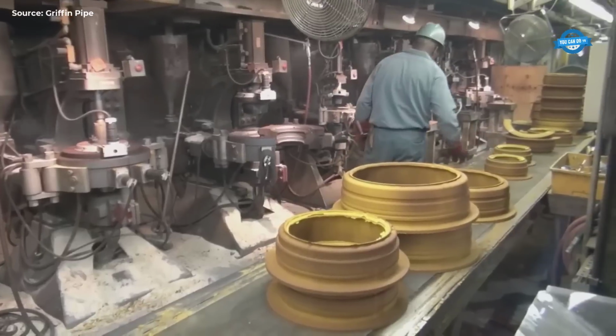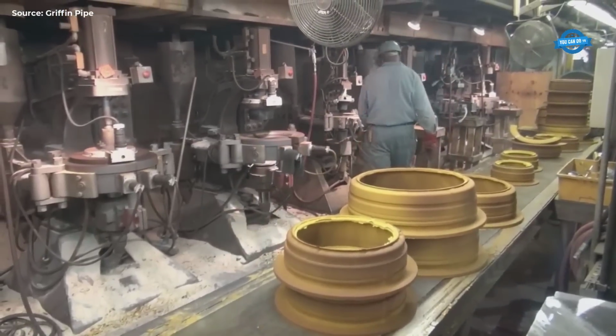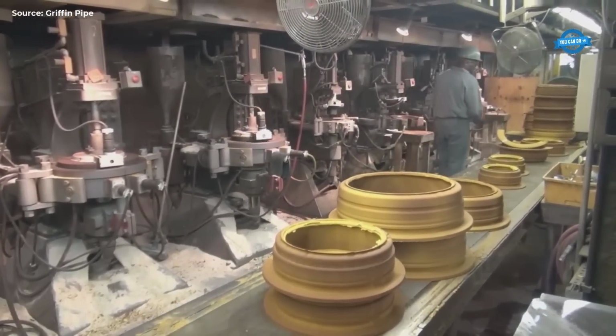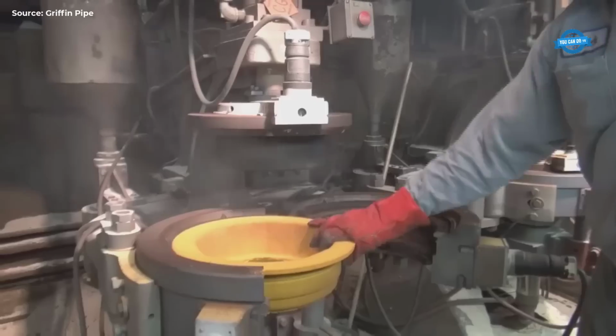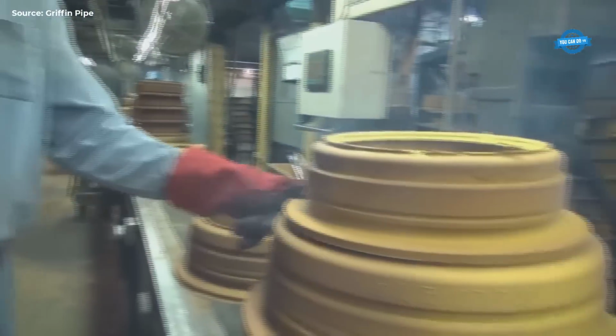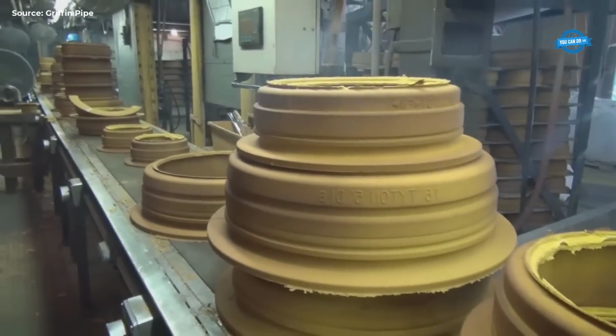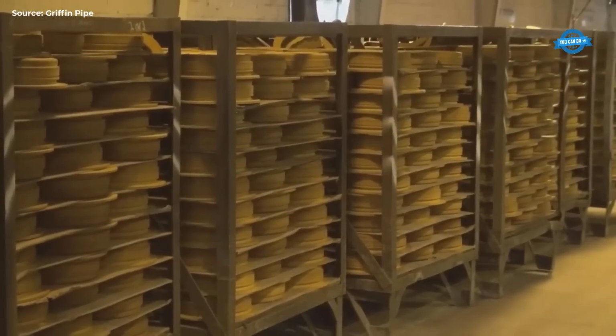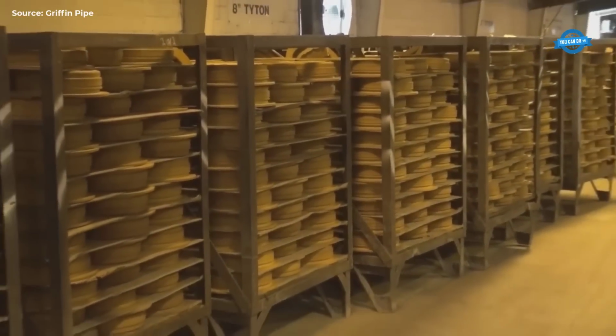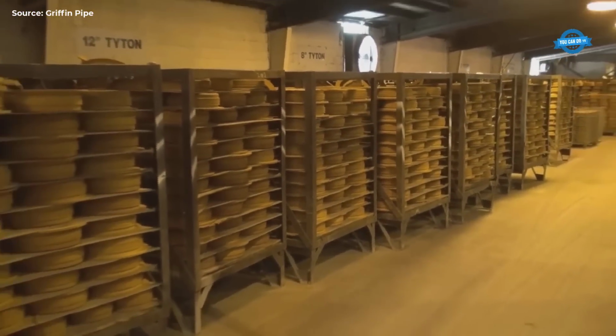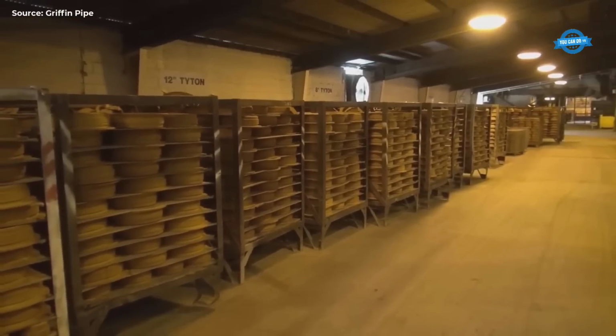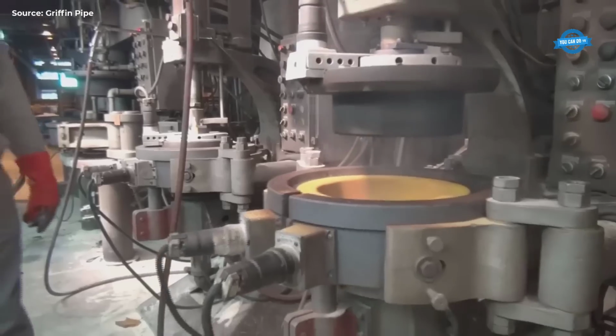Mold and sand core. The casting machine operator begins by placing a sand head core into the bell end of the steel mold. These sand cores, formed from sand bonded with resin, are critical in shaping the bell and gasket seating area of the pipe socket. The sand cores are produced in a machine similar to a large waffle iron, where they are heated to set and harden.